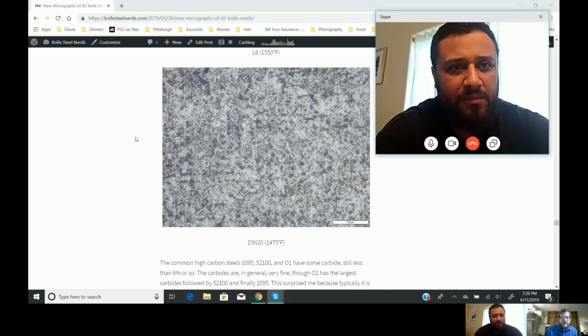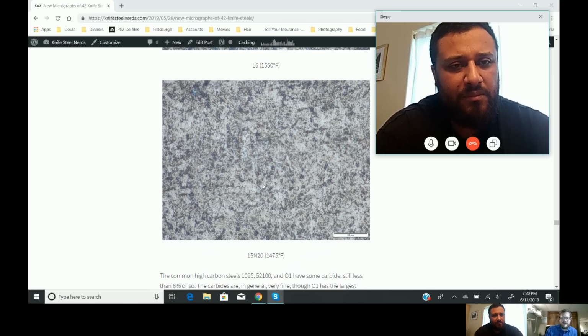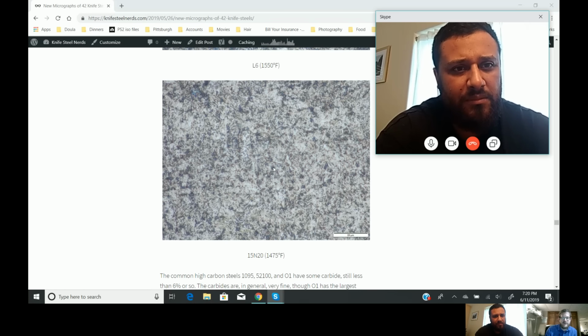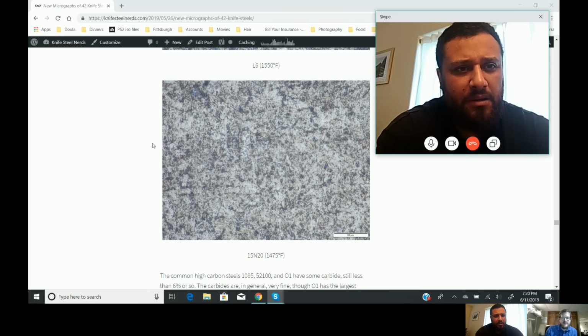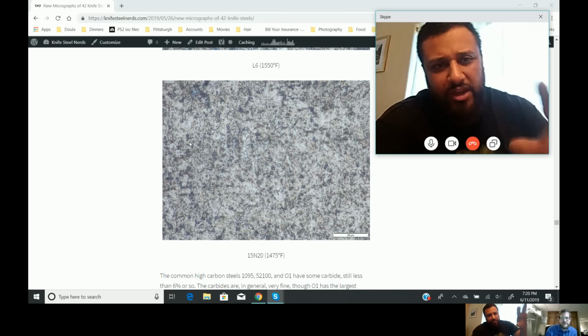Then 15N20, it's kind of like L6, but it's just carbon, nickel, manganese, silicon. And you can see here that some of those blue areas are surrounding carbides, so it could be kind of an etching response when it's near a carbide. Okay. So again, that's why I can't really tell what it is.